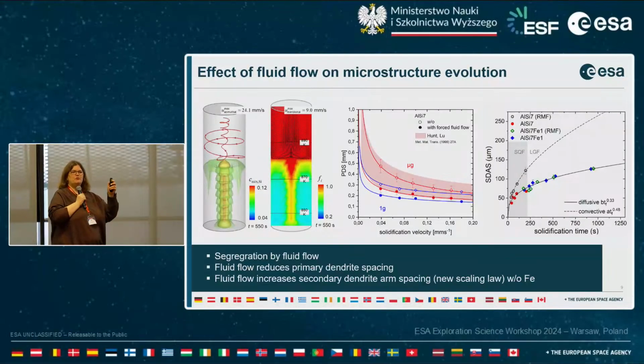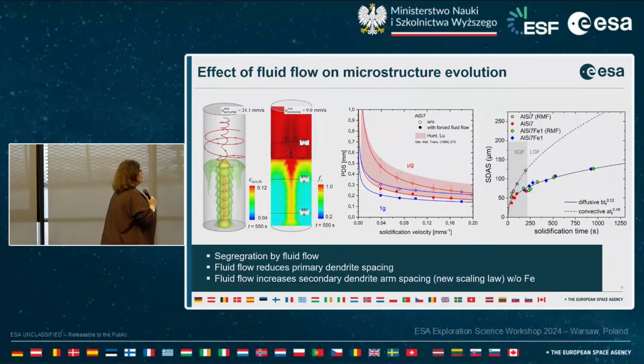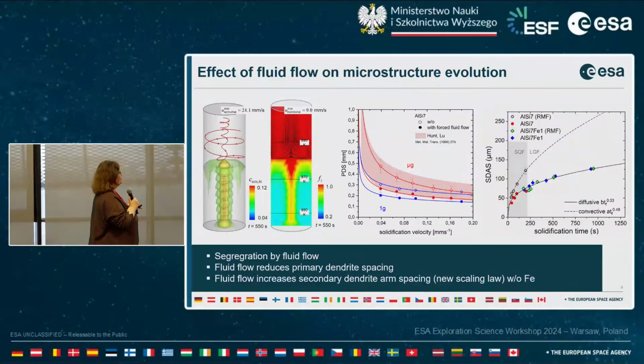Okay, this is, let me say, a macrosegregation or macrostructure effect coming out to the microstructure. And I think everyone in the room knows how to characterize such a dendritic microstructure. One parameter is the primary dendrite spacing. You can measure the space between the different stems, plotted here versus the different solidification velocities, in principle the furnace movement velocity. Here for comparison, microgravity experiments, samples solidified under pure diffusive mass transport conditions and with fluid flow. And you see that when we switch on the rotating magnetic field, the spacing is drastically decreased. This is one important result of these experiments.